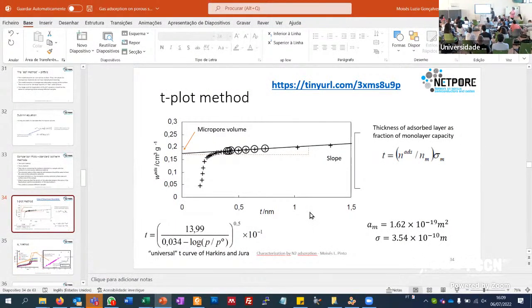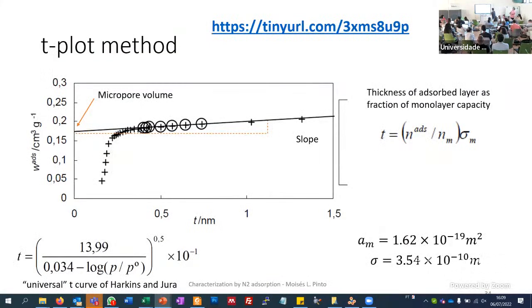So, with this method, we can calculate the micropore volume. We could also, from the slope, calculate the surface area, the external surface area, yes? Usually, if you have a very microporous material, the external surface area is very small compared with the value of the area obtained from the BET equation. Yes?